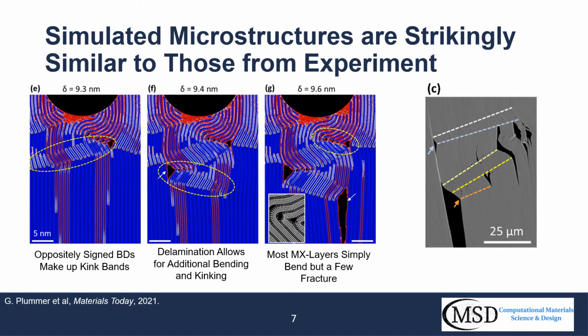Taking a close look at the numerous kink boundaries reveals that most of the layers simply bend, as we see in the SEM image, but there are a few which have fractured as well, which look a little bit more like the high-res TEM image.